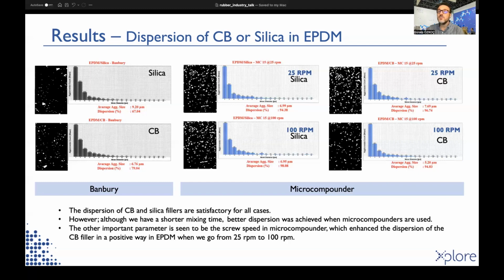Please remember that these two types of mixing were not optimized to get the best mixing. However, we experienced before that these two routes work well for similar mixtures. The other important parameter is the screw speed in the microcompounder, which enhanced the dispersion of the carbon black filler positively in EPDM when we go from 25 RPM to 100 RPM. On the other hand, increasing screw speed did not influence the dispersion of silica that much, since the dispersion process of silica in EPDM is thermodynamically driven.